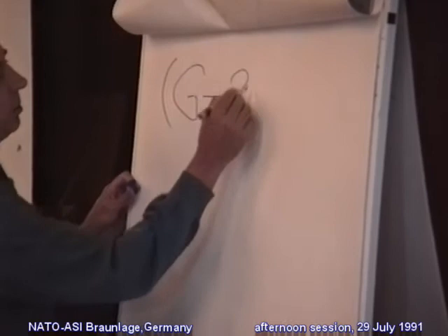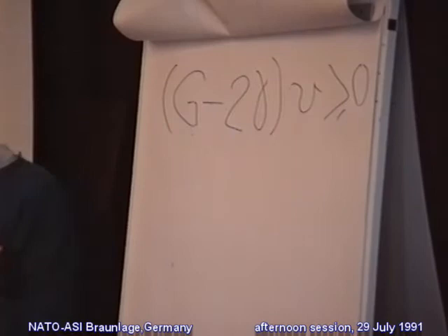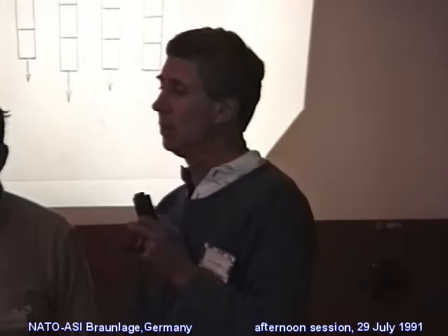Perhaps I could just go on here. It says that this has to be greater or equal to 0. And this is Griffith's law re-expressed in the second law of thermodynamics, with very subtle implications as to exactly what this means. But it does mean that you can run this crack forward and keep in a state of thermal equilibrium. Mechanical equilibrium, when you reduce the temperature to absolute zero, we have to overcome these energy bumps.